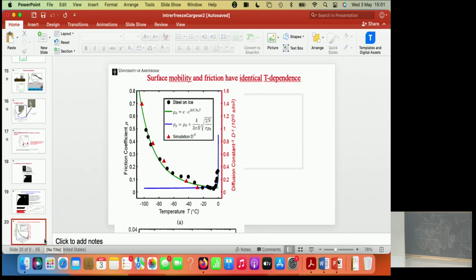And so at that point we did a little simulation together with the group of my brother of the mobility of the ice molecules on the surface of ice, and we see a direct correlation between the mobility, here expressed as the inverse of the mean square displacement per unit time, and this Arrhenius friction coefficient. But again, the diffusion coefficient in the simulations is not exactly that which you would need for simple surface diffusion. And so I think the million-dollar question is now, okay, it appears that stuff can move on the surface of ice, but what is actually the mechanism?